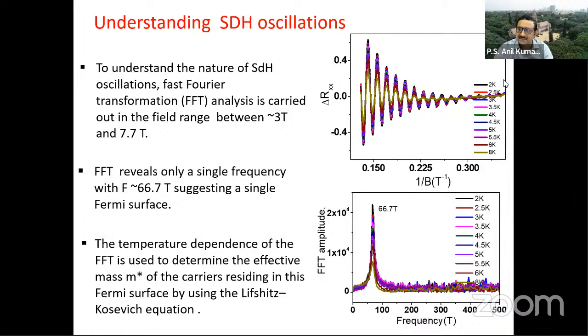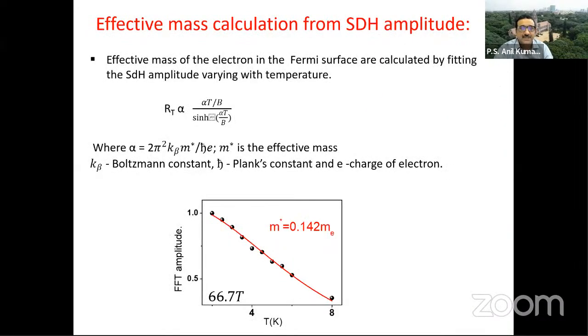We have done it at different temperatures. First of all, you can do a fast Fourier transform, and you get the frequency, which is 66.7 Tesla. If you analyze the amplitude of this frequency as a function of temperature, you can talk about the effective mass of the charge carriers in the system. With a proper analysis, we are getting the effective mass of the charge carriers as 0.14. So this is one result that we are getting.